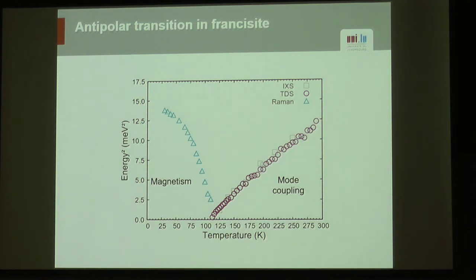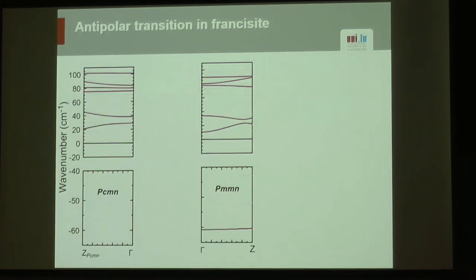So with this, I would like to go back now to the phonon calculation that you've seen earlier. What we wanted to do was take those calculations and go a bit deeper into the analysis, check the atomic motions involved, and see if we can say something about the atomistic picture. Here you have the relevant pieces of the phonon branches. This is for the high symmetry phase. This is the low symmetry phase. To make it more easily comparable visually, this has been calculated already in the double cell, which makes the comparison easier.